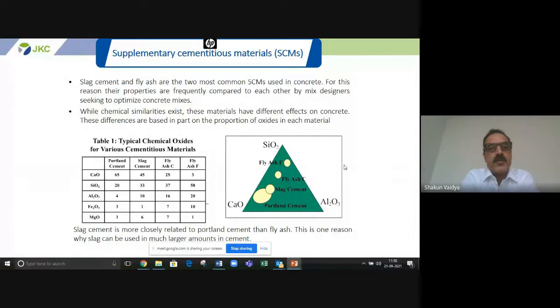And while slag is rich in lime, as you can see, Portland cement is rich in lime, and then silica is also there. In fly ash, you can see it is rich in silica but has negligible lime quantity. In slag cement, it is rich both in lime as well as silica. So these are typical chemical oxides for various SCMs.